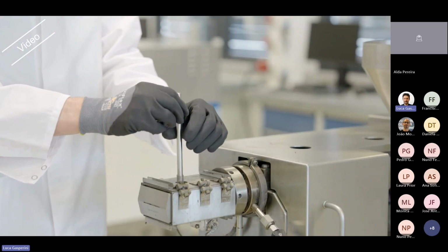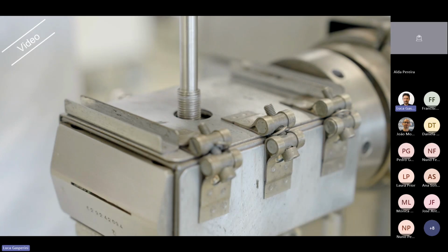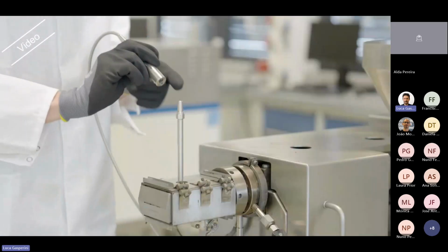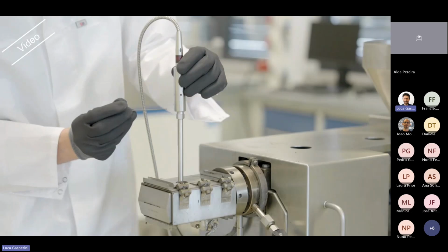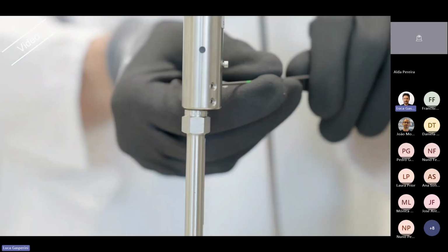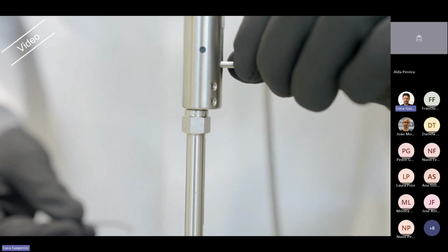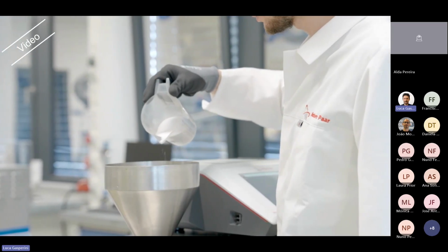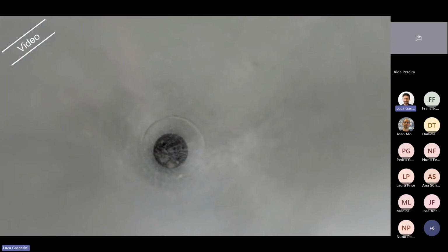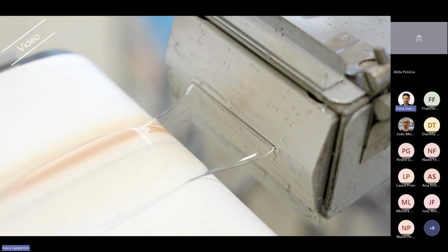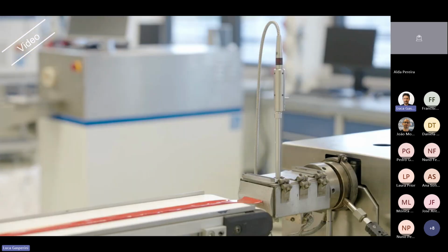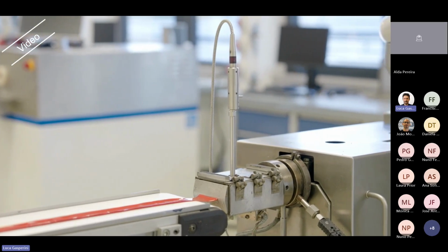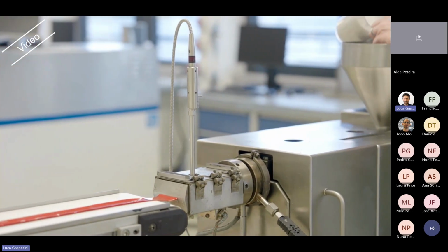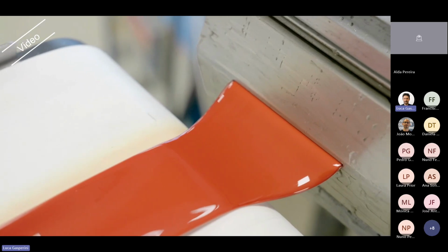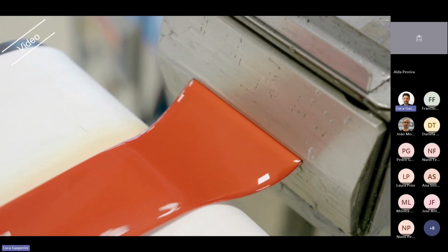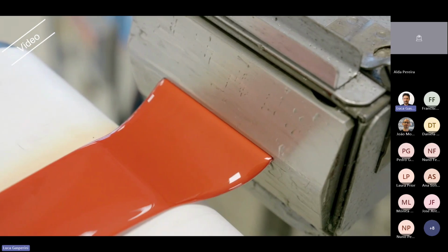This is just to show you how you would mount the Raman, or connect the Raman with an extruder. You cannot just put the Raman probe into the extruder due to the pressure and the temperature influences. So we're using a fiber probe, an immersive probe which you can put directly into the extruder or at different positions along the extruder. Here we were extruding, I think it was LDPE, or different kinds of polymer recipes, and we were measuring the Raman signal directly in the die head. It's an in situ, real-time measurement.